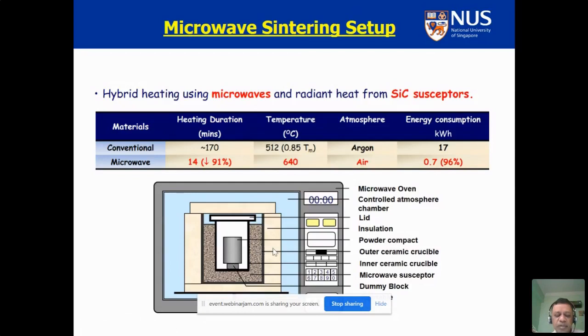And then you pre-calibrate the microwave for the time. So for example, if I had to reach 640 degrees centigrade, say for aluminum or magnesium, I can reach it in 14 minutes. So that means my sintering time is 14 minutes. That gives me almost 91% saving in the heating duration. So the turnover time is much faster, 90% faster. And then the energy consumption is 96% lesser in microwave when compared to the conventional mode of heating. So in both ways, I reduce the cost of the product.